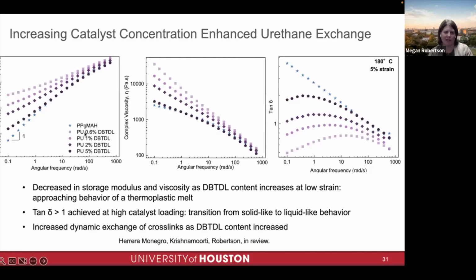Our study was actually done with the lower level. Everything I showed you was this 0.6%. At that low level of catalyst, under these linear rheology conditions, this material doesn't flow exactly like a linear polymer. But under the higher strain of melt compression molding, for example, or under the forces and strains in an extruder, the material will flow like a viscoelastic or linear polymer. And you see this transition from a solid-like to a liquid-like material just by adding more of that catalyst.